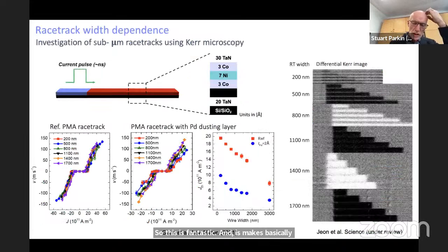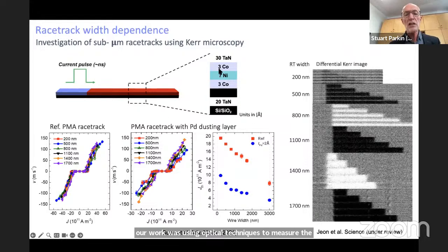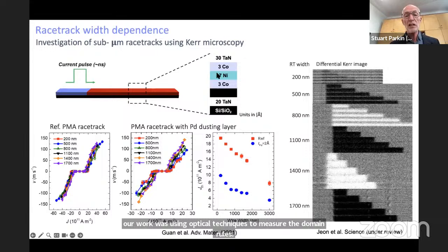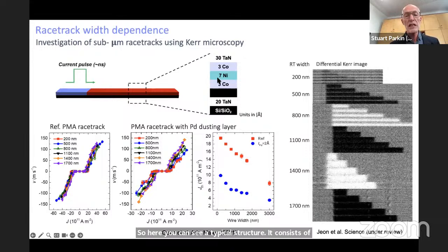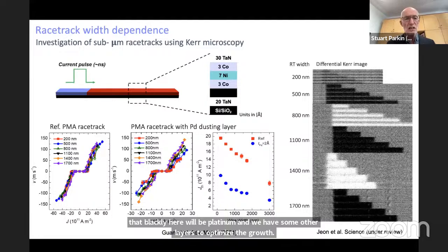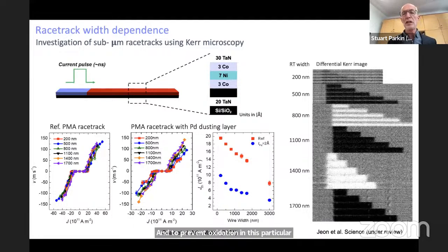So a lot of our work for all those years was using optical techniques to measure the domain walls. So here you can see a typical structure. It consists, in this case, of 3 angstroms of cobalt, 7 angstroms nickel, 3 angstroms cobalt. So it's a very, very thin magnetic layer. The black layer here will be platinum. And we have some other layers to optimize the growth and to prevent oxidation. In this particular case, this is just a simple ferromagnetic racetrack.